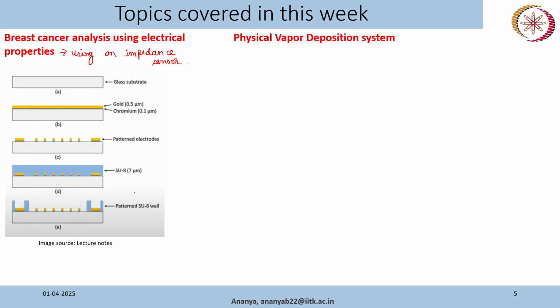For this work, they are using 7 micrometer thick SU8. This is relatively thick. We normally don't use this kind of thickness for photolithography, but they are using it in this sensor as a well to hold a biological sample. That is why they are keeping the thickness at 7 micrometers. I'm sure they have optimized these values, so they need this much thickness for the sensor to work properly. After that, they did lithography and made the SU8 pattern.